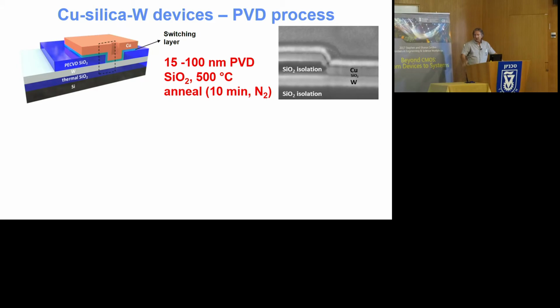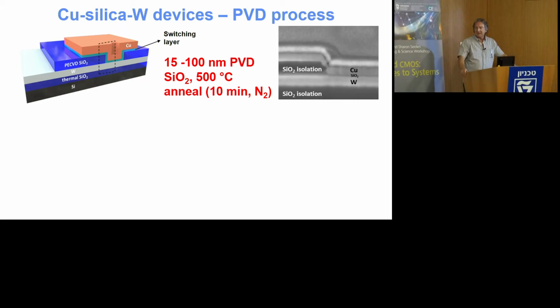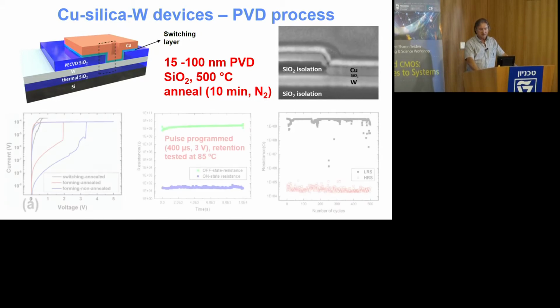So, it kind of makes the subsequent program of these things a lot simpler as we go along. But the penalty is you're using a high temperature in the back end of line. The key thing is, though, it has to be fluffy. It has to be a low-density oxide, typically in the order of 15–20% less dense than a typical thermal oxide, and that allows it to switch very, very well. So you have to adjust your deposition parameters to achieve that.